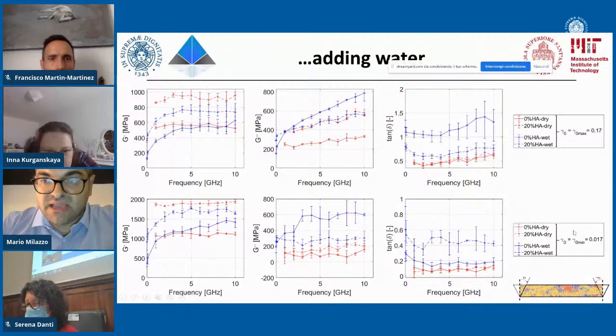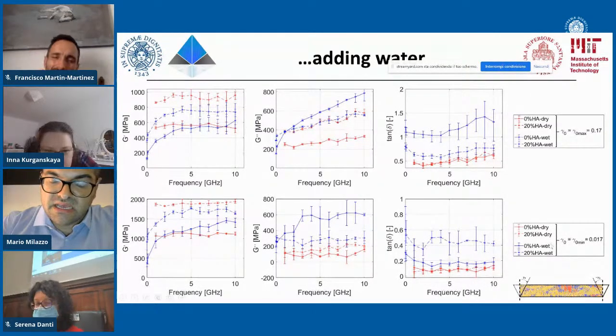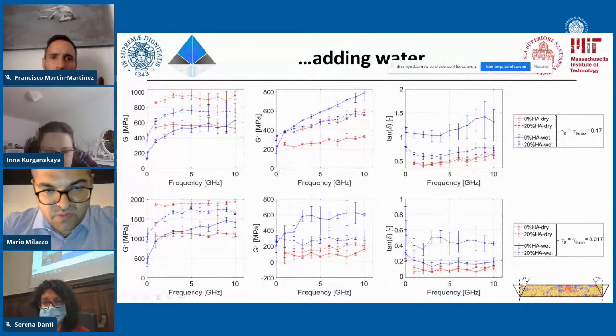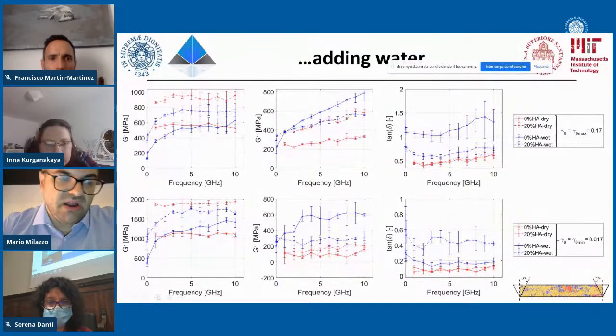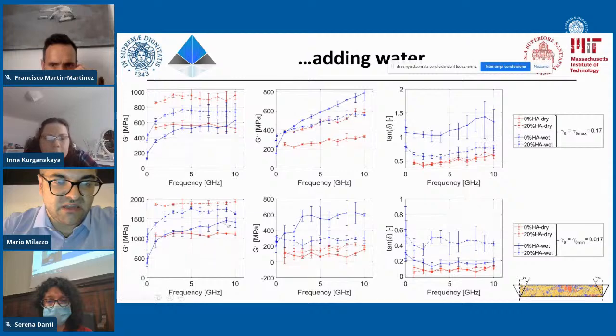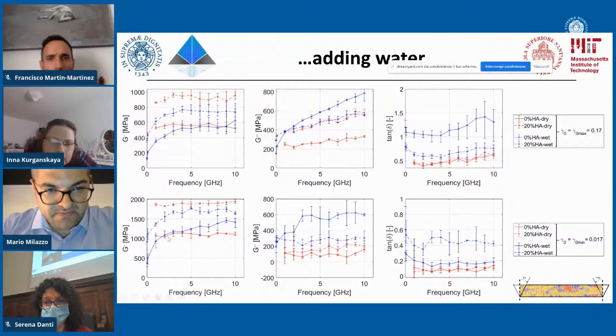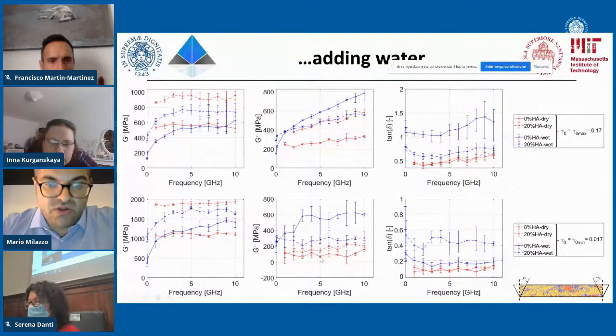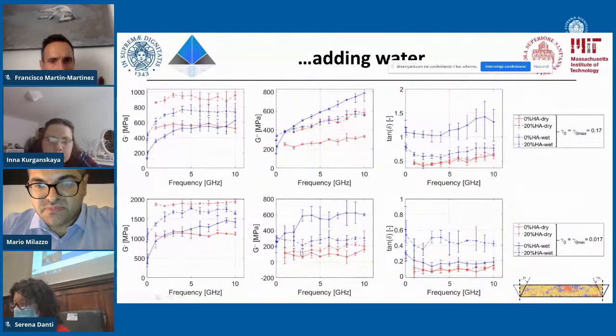The same looking at the loss angle, we can see an almost similar scenario in which we have a saturation of the elastic component towards the high frequencies, while the dry structure always has an almost constant value. And water, of course, is increasing the viscous behavior of the material.